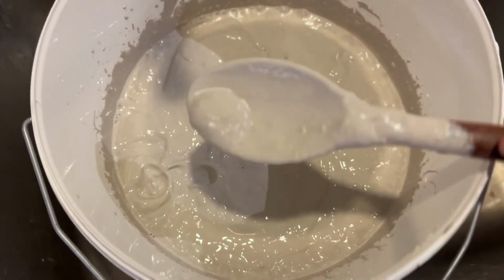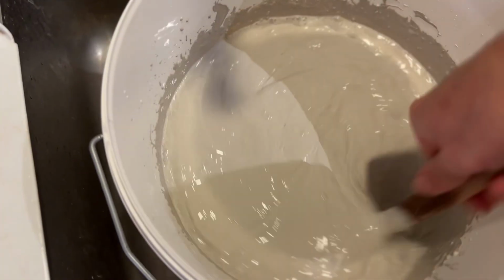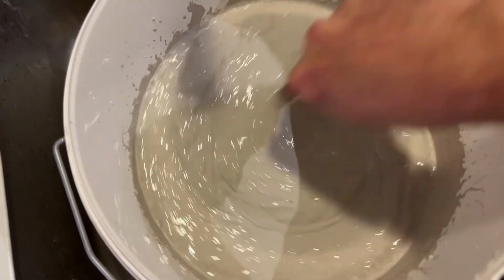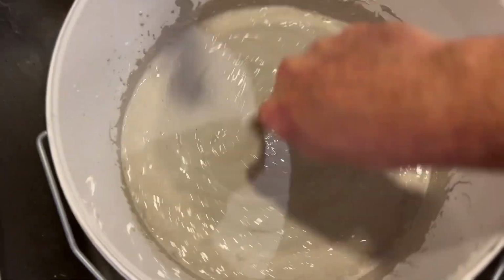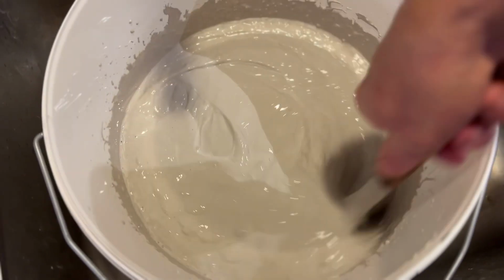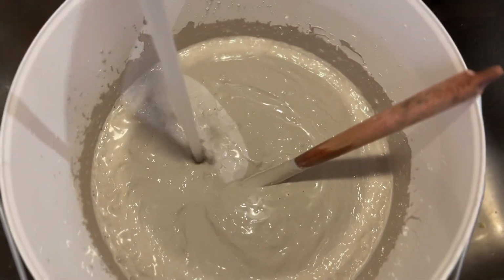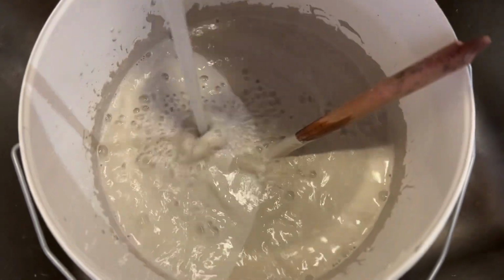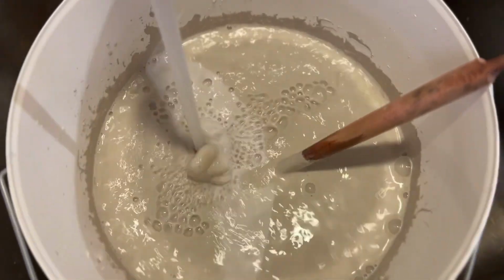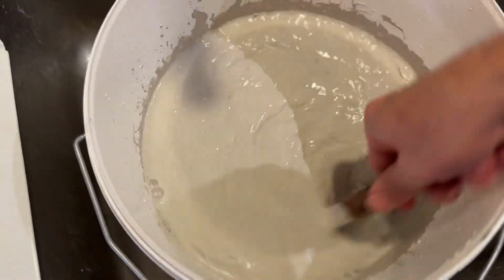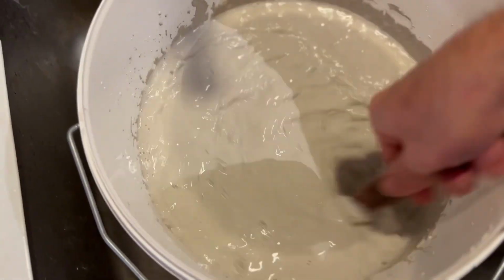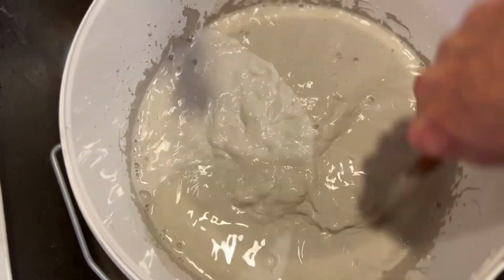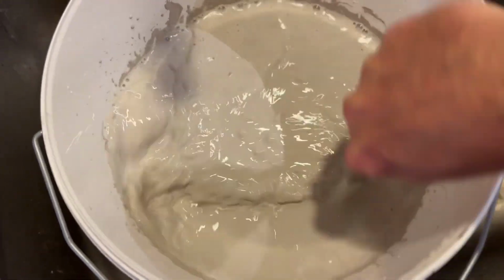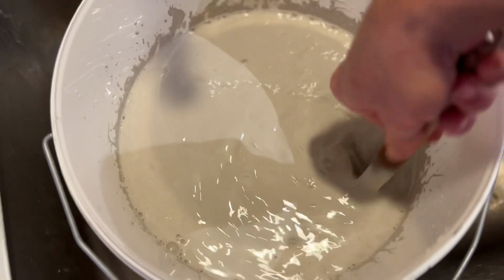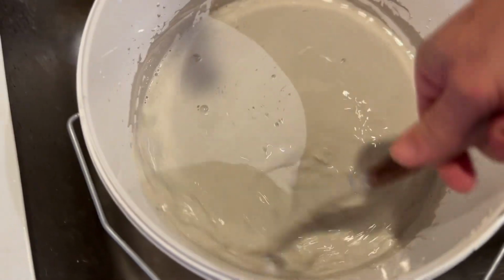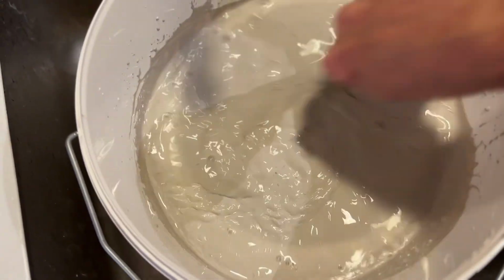Of course, it is way too thick now. It needs to be much thinner. So before we start actually measuring the thickness of the glaze, I can add more water with no problem. So definitely going to have more water. I'm just going to add a little at a time, because as I mentioned before, I don't want to add too much water either, because it is much easier to add water than it is to remove it.